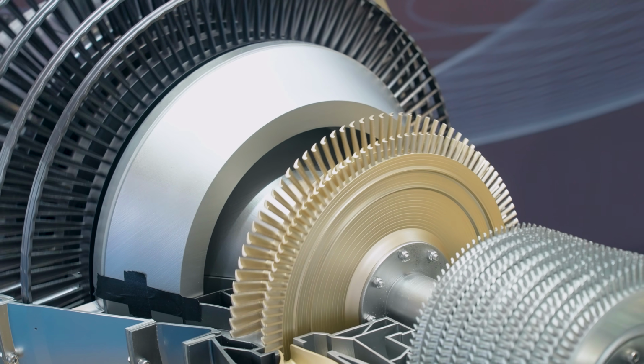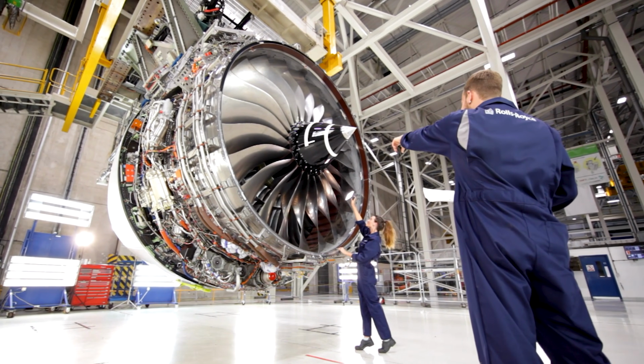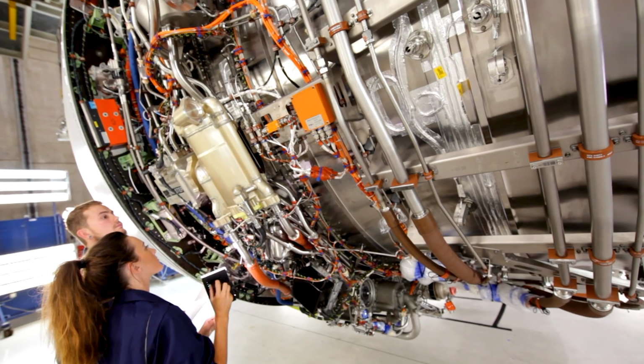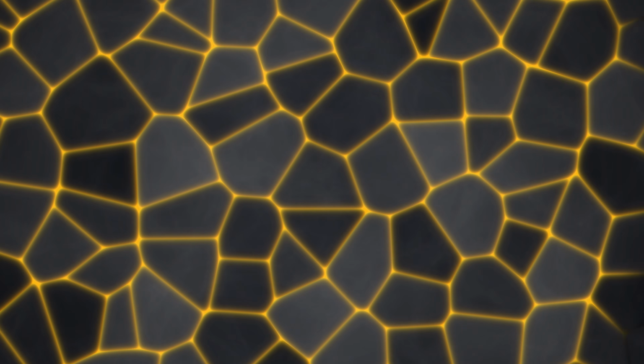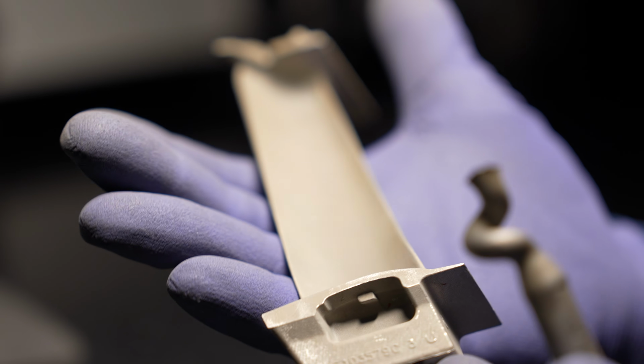Today, after decades of development, over 95% of blades can be cast successfully as single crystals. Just think about how incredible that is. We've gone from a turbine blade that contained on the order of 50,000 crystal grains down to just one. When we grow these things, they don't solidify as a uniform front.